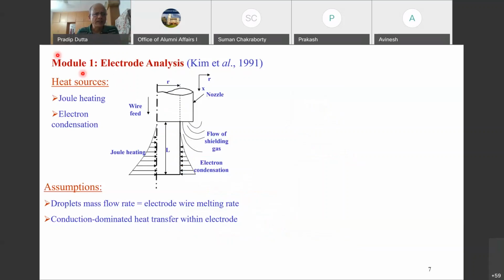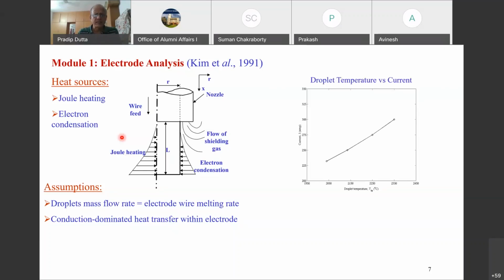First, let's take module 1, electrode analysis. There have been many different types of electrode analysis, but we tried to adapt something which would fit into our model. That is, we wanted to know what is the enthalpy of the droplets or the rate at which the droplets are falling on the weld pool. So that prediction was first done using electrode analysis. Again, this is a thermophysical analysis that we had done, a CFD modeling of the electrode itself, along with some other physics of arc that goes into it. And then this would generate something like droplet temperature versus current, and we got a healthy trend, which is the higher the current, the higher is the droplet temperature. And as you see there, droplet temperature upward of 2000 degrees is produced.